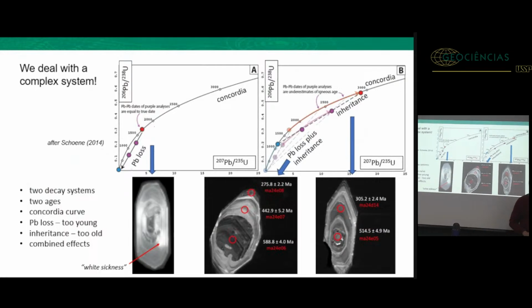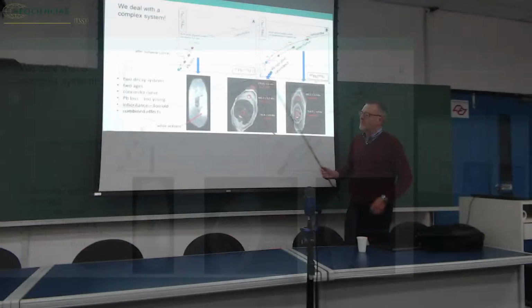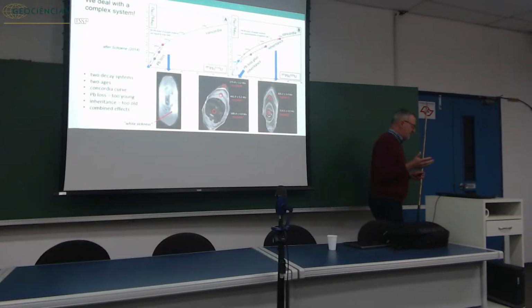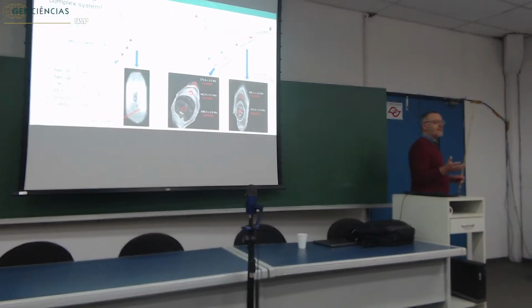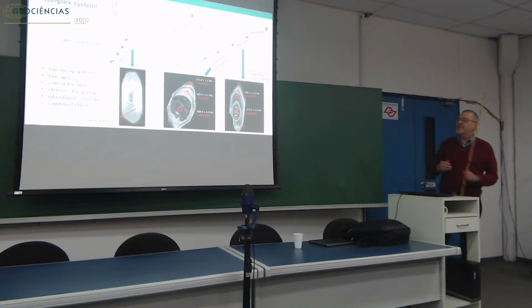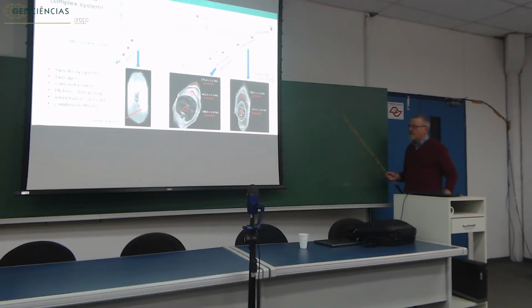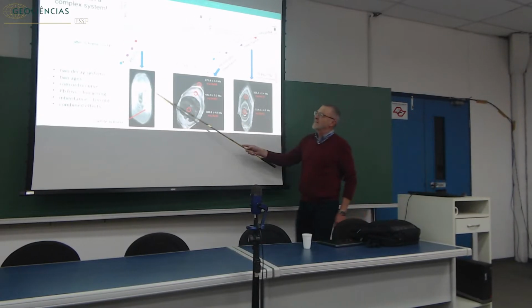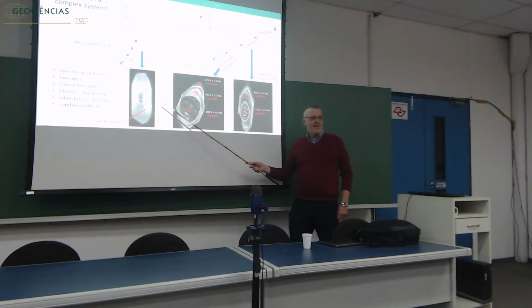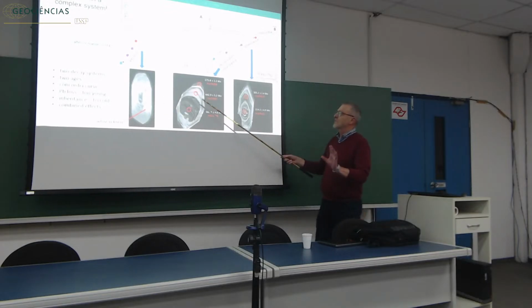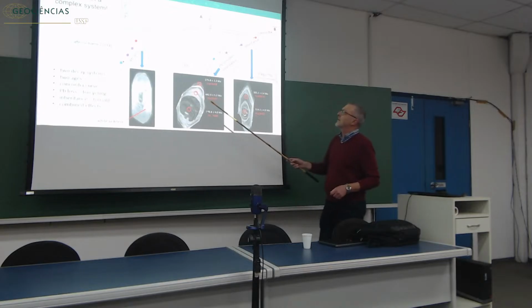So I kind of coined this term of white sickness, which is now used by some people. These are areas of the grain which underwent maybe dissolution, reprecipitation, or recrystallization. We actually don't really know. But when I see such grains, I smell they will have lead loss. Should not shoot with the laser onto such grains.